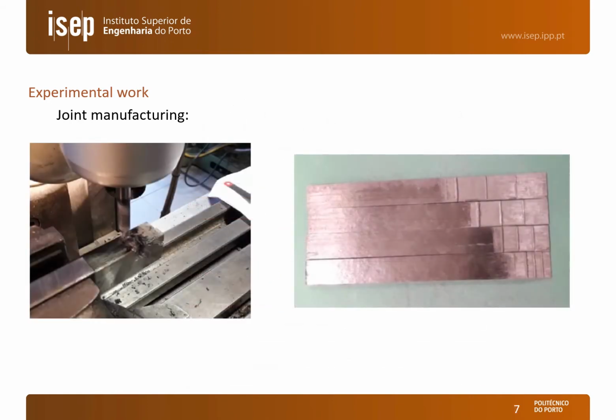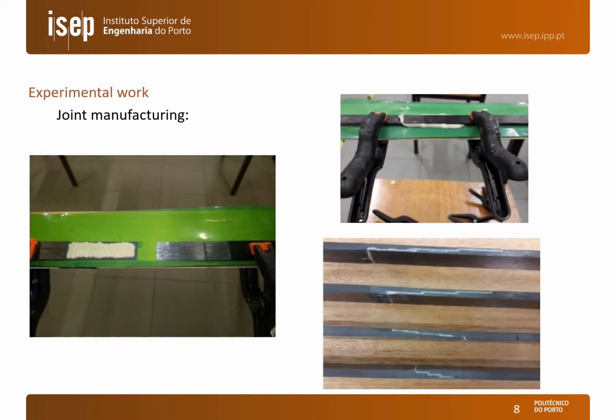Some details on the manufacturing of the joints. We can see milling of the steps in the composite adherents in a conventional milling machine and with a carbide tool, and the end result to the right, in which we can see the three steps with 4 different overlap lengths. Here we can see details of bonding. In the upper image we can see the apparatus for bonding the joints, and in the lower right figure the complete and prepared joints ready for testing, one joint for each overlap length.